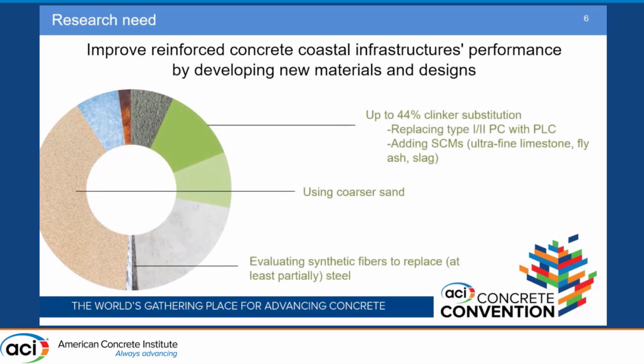So we said, okay, how can we address both of these challenges? We tried to improve sustainability of UHPC formulations by replacing the traditional type 1 and 2 cements with PLC and adding low carbon SCMs such as ultrafine limestone, fly ash, and slag. We used a coarser sand, and we addressed also the cost issue, evaluating synthetic polyethylene fiber to replace at least partially the steel ones.